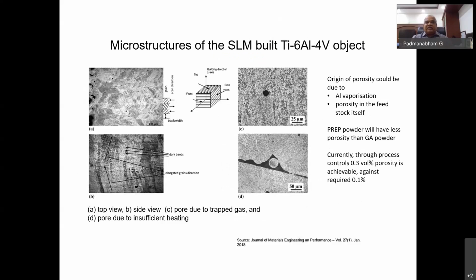Just look at this microstructure when you build layer by layer. I already talked about the porosity formation, but here we also found a difference depending on how the powder is made. The percentage porosity is varying depending on what process you have used.